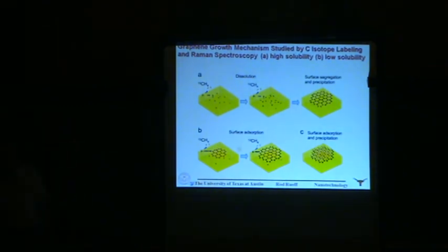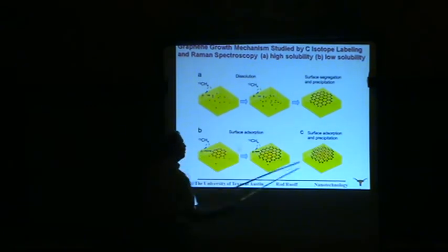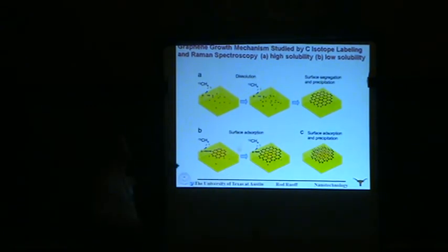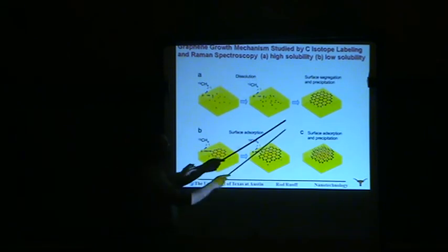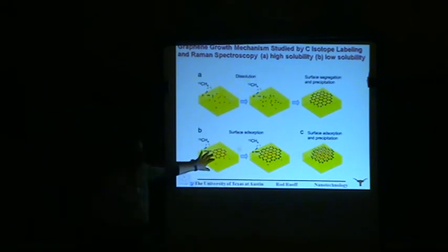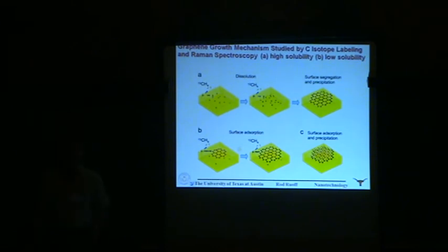Excuse me. So this picture that we have for two different systems, we did the experiment on nickel and we get one color. The reason why we get one color instead of two colors is because we get isotopically scrambled graphene, because the mechanism is entirely different. The atoms go down into the nickel, they move around and diffuse, and when they precipitate out upon cool down, of course they're isotopically scrambled. Whereas this is the picture with copper, where we have surface growth. So both techniques are valuable and both are interesting.